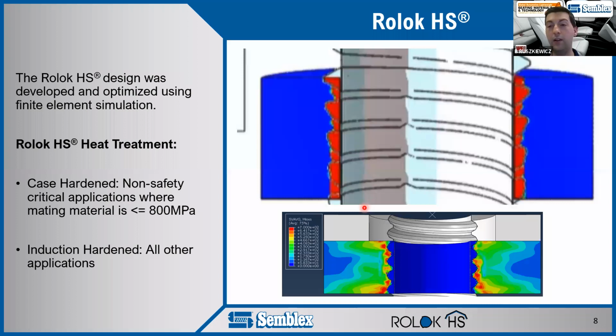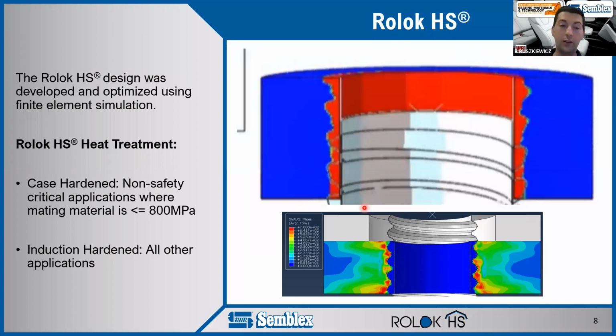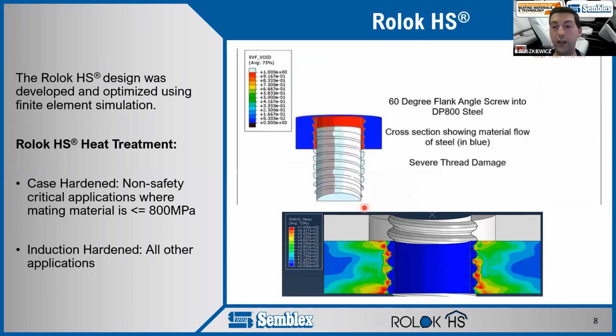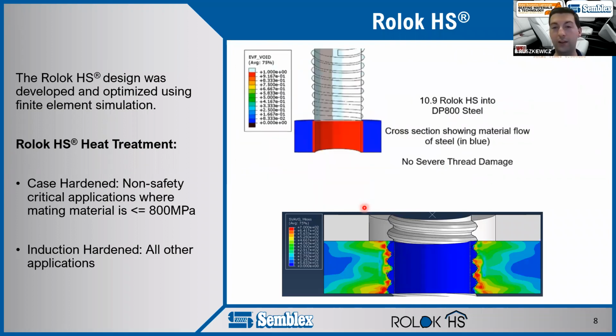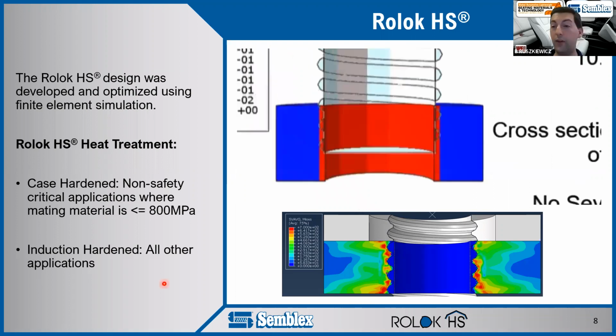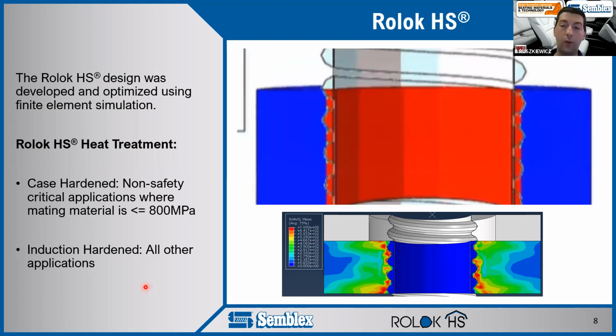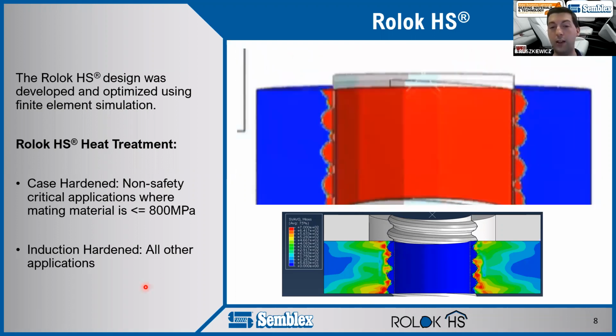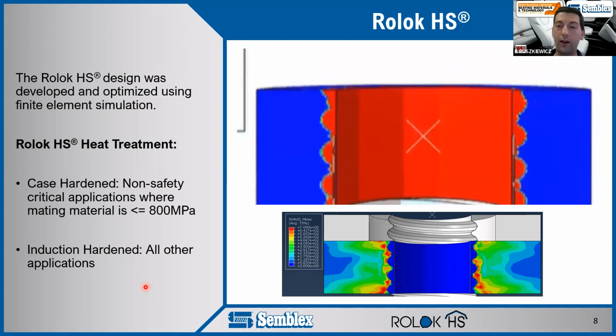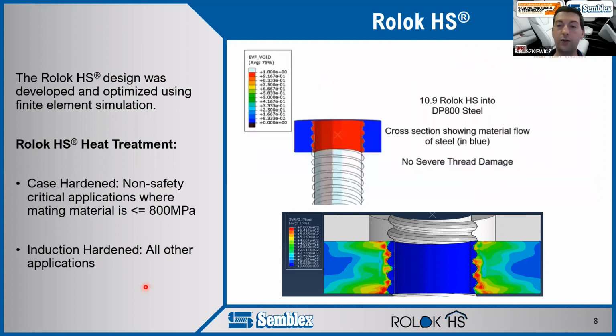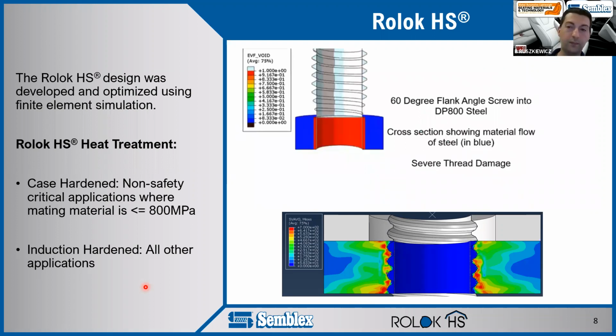Now, as far as heat treatment goes, as mentioned, we're trying not to change these. So we're still using the traditional heat treatments you'll have on thread rolling fasteners. We recommend a case hardening for anything that's not safety critical and anywhere where your mating material is less than or right around 800 megapascals. For everything else, we recommend induction. We're also playing with a new heat treatment called austempering, and we'll talk about that later on. That's for very specific, very high-strength applications.